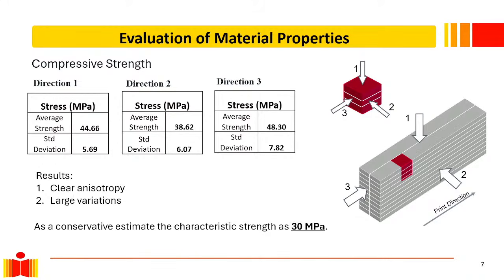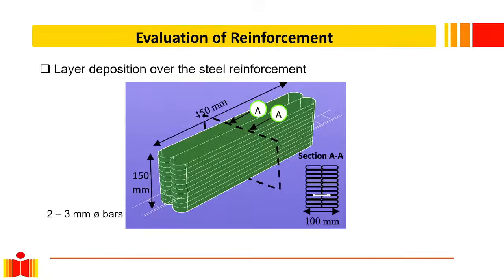So, being good engineers, here's what we did. We chose the weakest direction, which is direction 2, and then we said, well, we are going to take 1.65 times the standard deviation, move away from there, and define a characteristic strength that comes out to 30 MPa, and we thought we can't go wrong. So that's the compressive strength of our printed filaments, and that's what we are going to use and proceed with our design.